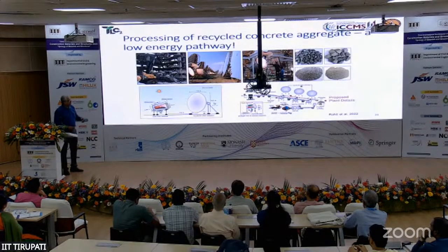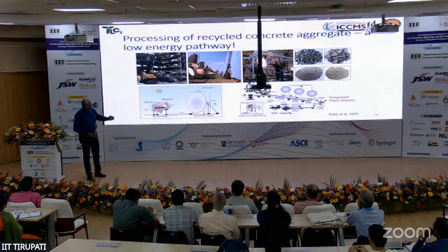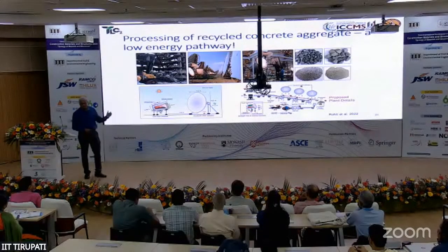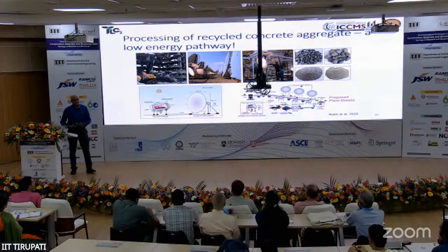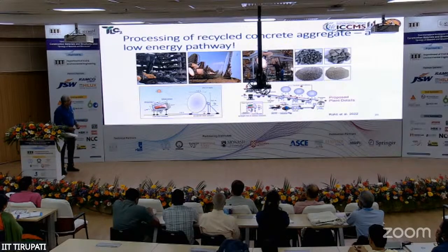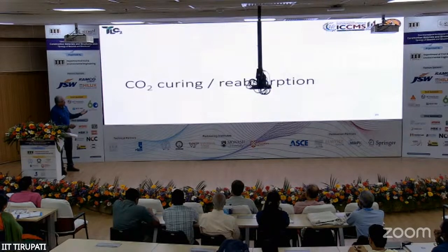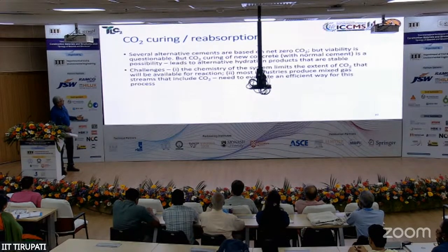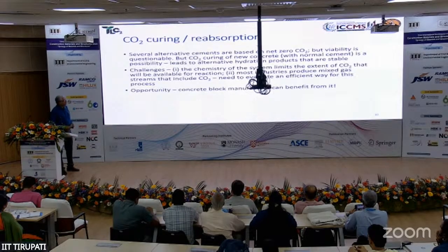One example of work that was done by my colleagues, Professor Gettu and Professor Surender, is to look at using concentrated solar to break down the mortar from the aggregate. And using this process, they were able to supply sufficient heat for a thermal beneficiation and later crushed to obtain perfect aggregate, fine aggregate, and recycled concrete fines. So this approach is something that needs to be scaled up. We are still looking for possibilities with which we can scale this up. This was done at a facility in Mount Abu in Rajasthan. And CO2 curing reabsorption, I'm not going to talk too much about it, but yeah, several alternatives are based on net zero CO2.